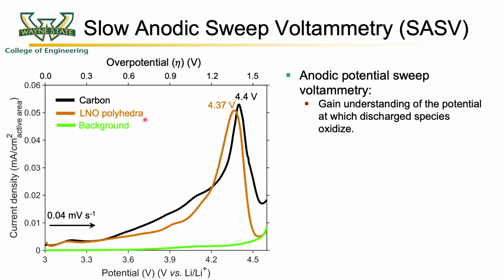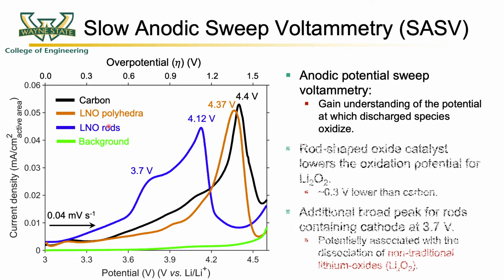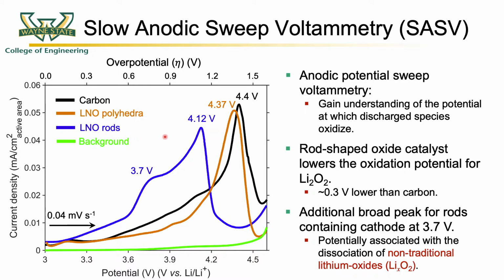Upon incorporation of polyhedral shaped La2NiO4, a small reduction in the charge overpotential is observed, similar to our discharge charge studies, while incorporation of rod shaped La2NiO4 leads to a significant reduction in the charge overpotential, as well as the presence of a secondary peak at about 3.7 volts. This peak can potentially be associated with the oxidation of non-traditional species such as LiXO2, where X is less than 2. In other words, it could potentially be associated with the oxidation of non-traditional products like LiO2.